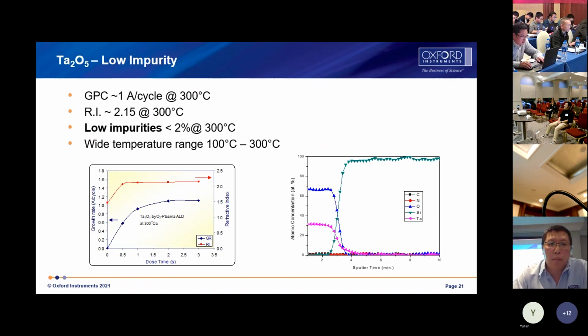At a higher temperature, we developed a process that gives low impurity tantalum oxide ALD film. In the SIMS data on the right-hand side, for the film deposited on a silicon surface, you can see very low signal levels of carbon and nitrogen.